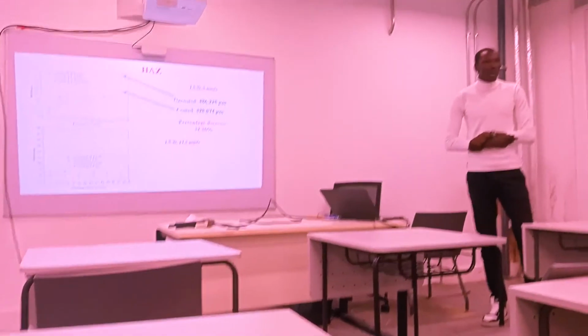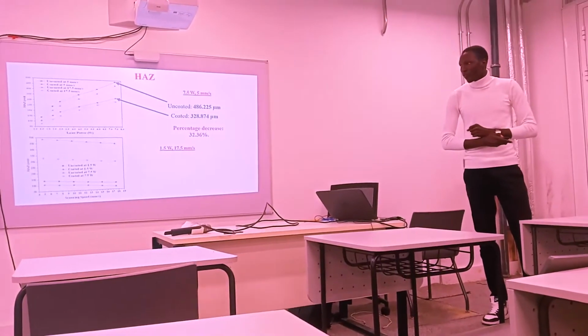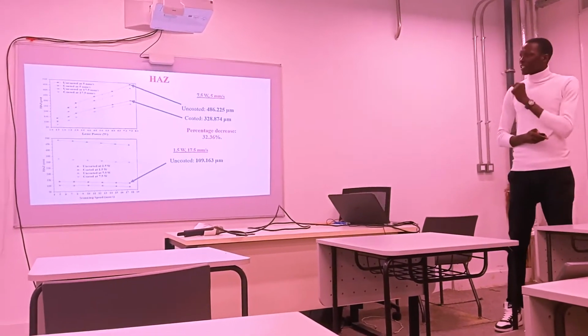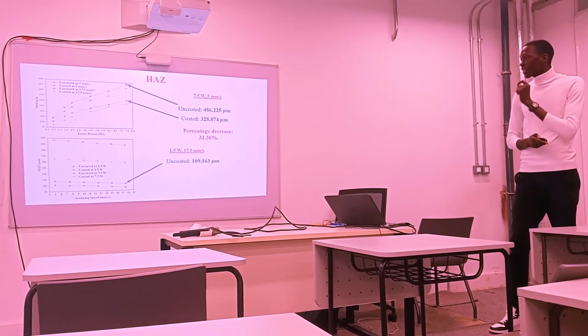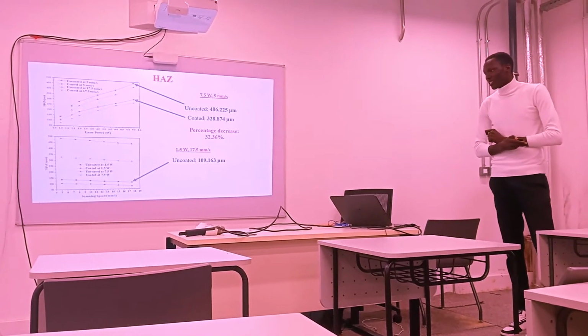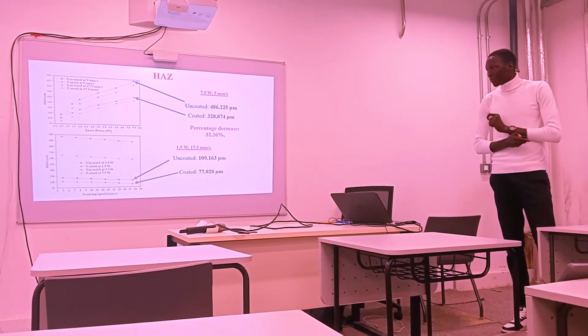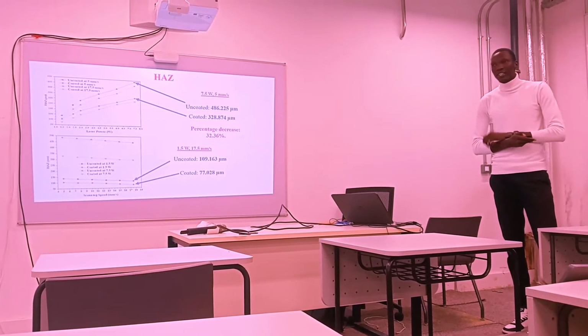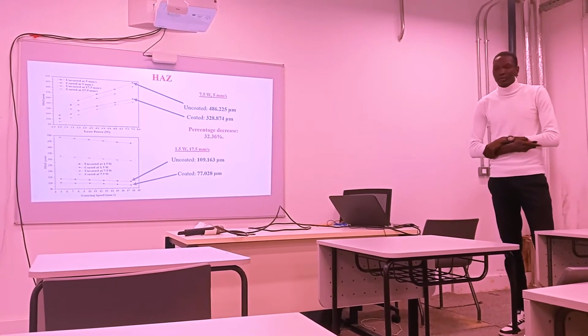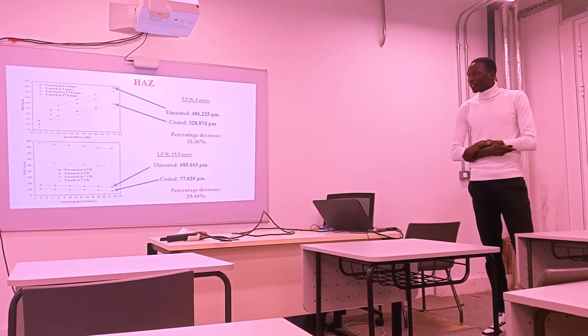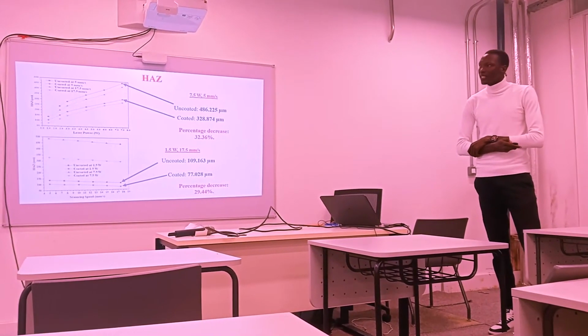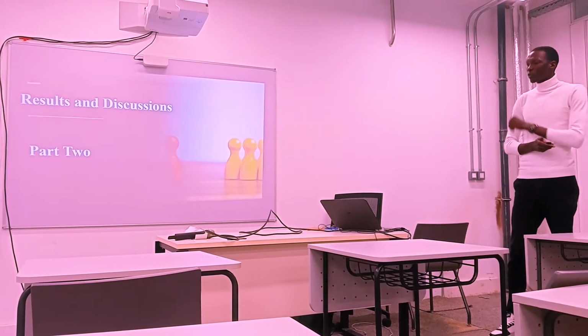Now, at minimum power and maximum speed, for the uncoated sample, we got 109.163 micrometers. And then for the coated sample, the value of heat affected zone was 77.028 micrometers, a percentage decrease of 29.44%. And then we move to part 2.